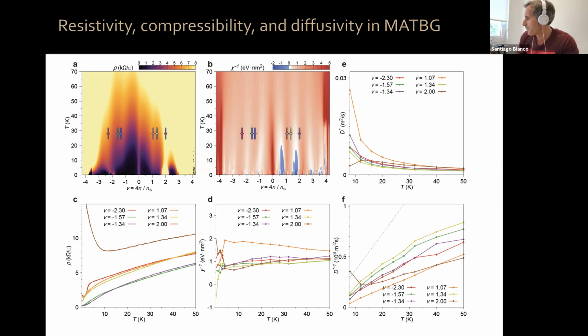Very interesting question. In a different experiment, in different samples than those where I showed the nematicity, with our collaborator Amir Jacobi, we have seen states in magic angle bilayer graphene which was partly aligned to the hBN substrate. With a small twist angle with respect to the hBN substrate, we have seen evidence for charge density wave states. People that do STM experiments, like I believe the group of Eva Andrei or Abhay Pasupathy, I forgot which of the two, it could be both of them, have also seen some evidence for charge density waves in the system.